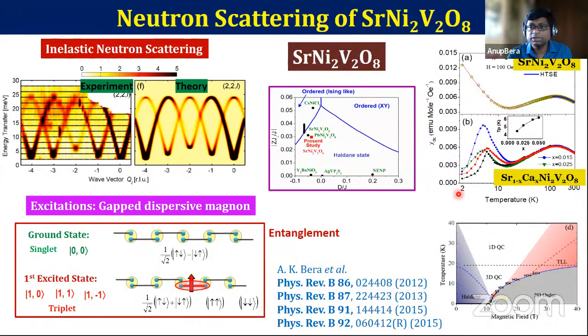Immediately we can see this is the parent compound. This is susceptibility as a function of temperature. The parent compound doesn't show any peak, but when we substitute some calcium, it starts showing a peak, which corresponds to the magnetic ordering. And you can see that with concentration, the magnetic ordering temperature increases.